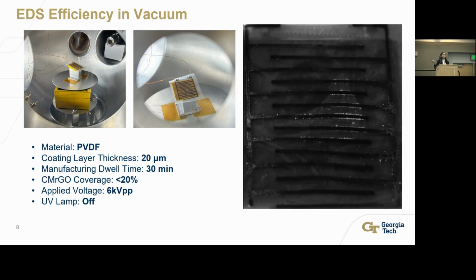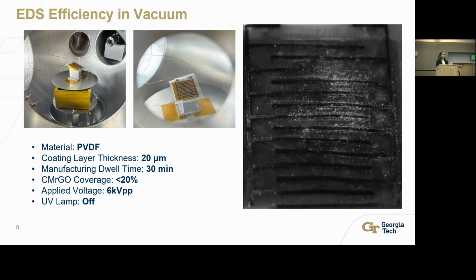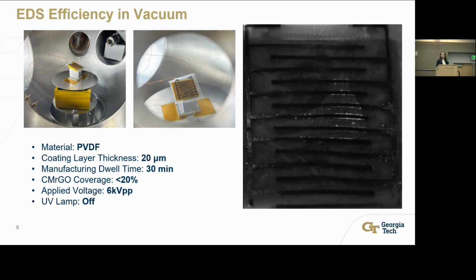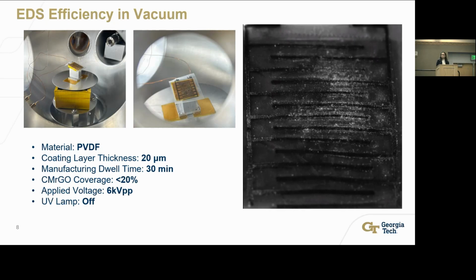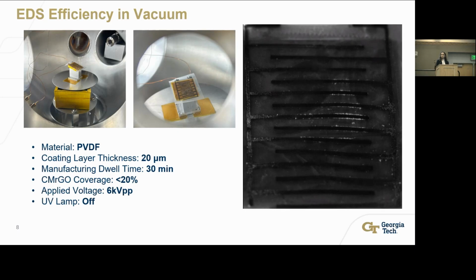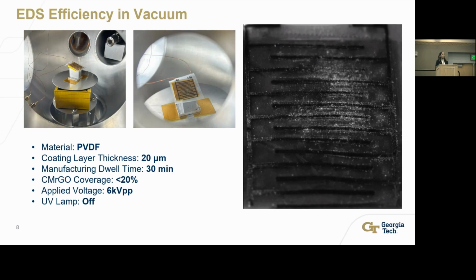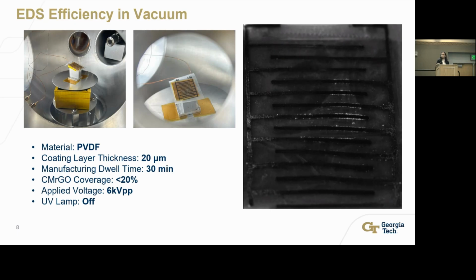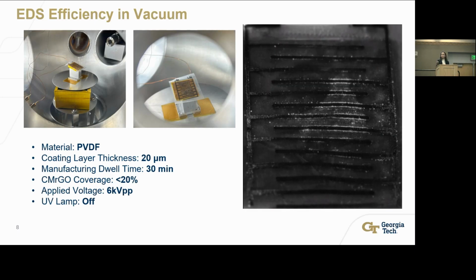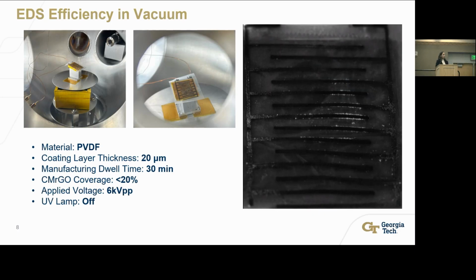On the right, you can see a looping video of our performance. And this is a PVDF sample with a coating layer thickness of 20 micrometers that was manufactured using the 30 minutes of dwell time condition to get the best seal possible. And this video belongs to an applied voltage of 6,000 volts. But we started this test at a much lower voltage, and we repeated many runs until achieving this video. And even though we ran many samples, we haven't seen any dielectric breakdowns or the sparks that you've seen in the previous presentation. So we are actually getting rid of the dielectric breakdown by encapsulating with a dielectric layer.